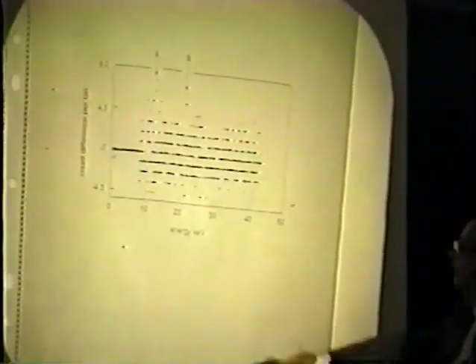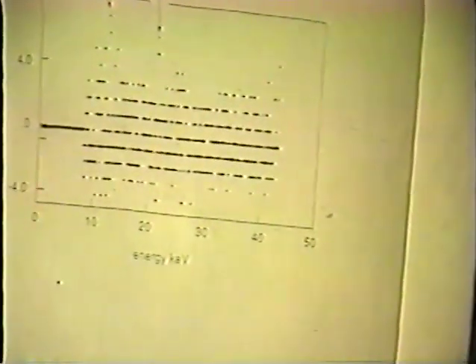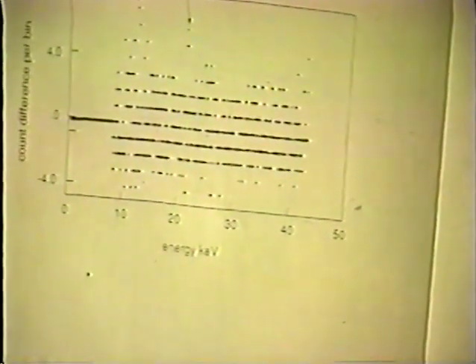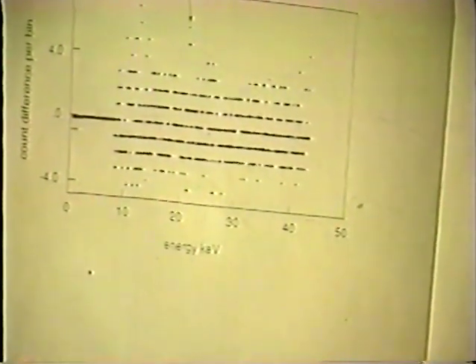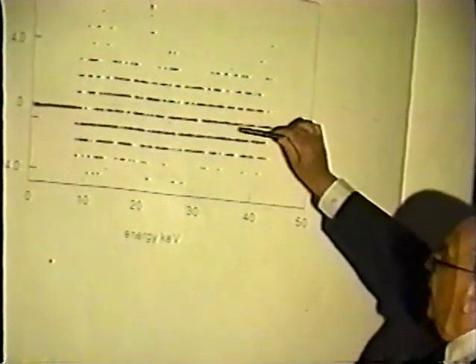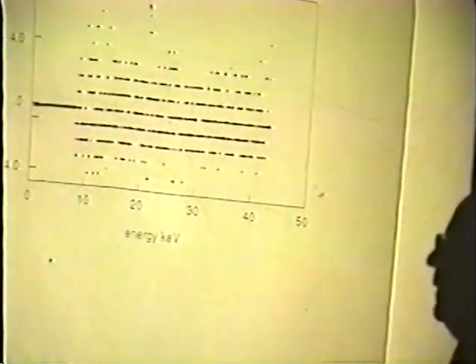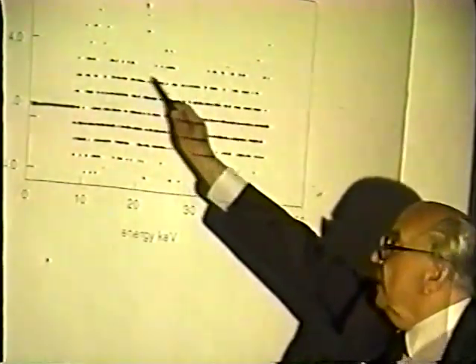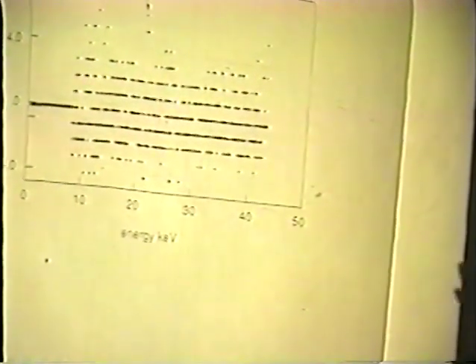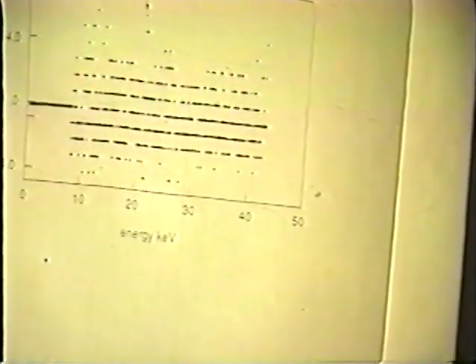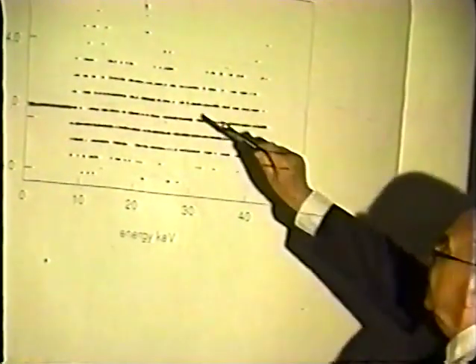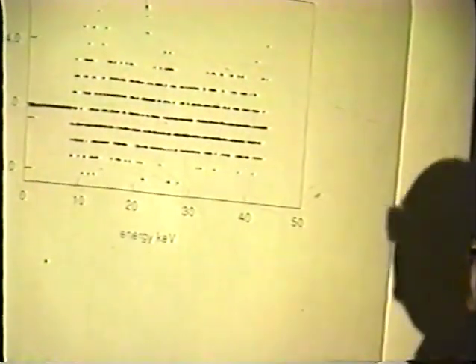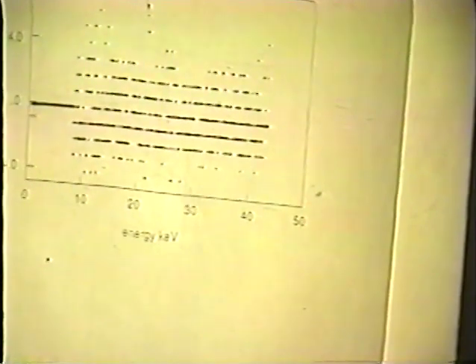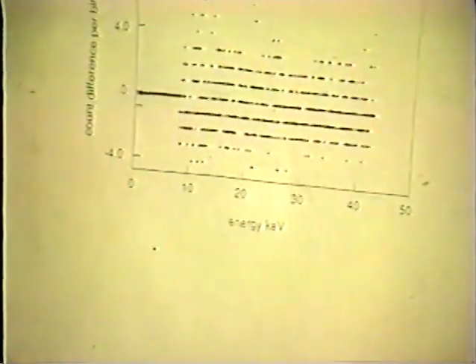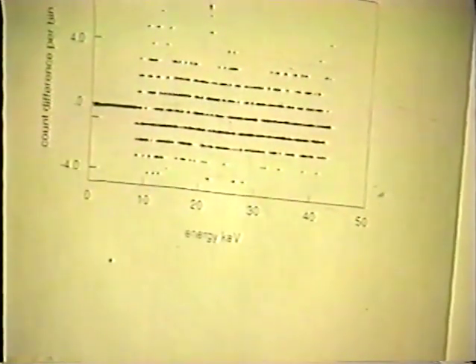Yeah. And here you have a count difference per bin. What we have done here, we subtracted the background, and you can see that there is an asymmetry here. That means there is some radiation throughout the whole range without any definite pattern, except here. Around 21 keV, we see a peak. Well, that would be associated with PdK alpha.